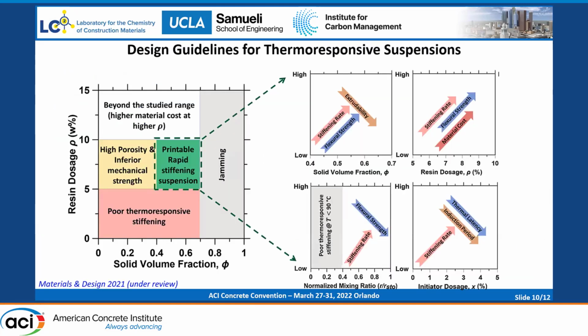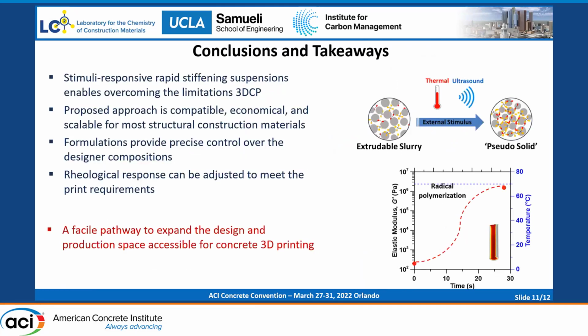So to conclude, we came up with design guidelines for these suspensions, where within the printable domain of this formulation, we show how various parameters can influence the thermoresponsiveness of these formulations. We have solid volume fraction, resin dosage, the mixing ratio, and initiator dosage. So depending upon the print geometry and the kind of stiffness we want, we can play around with these formulation parameters and control the stiffening response of these suspensions. With that, I conclude here.